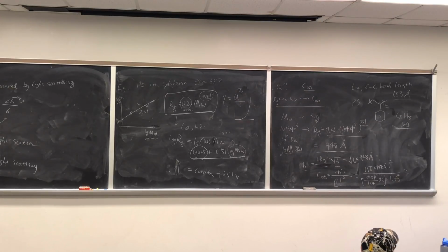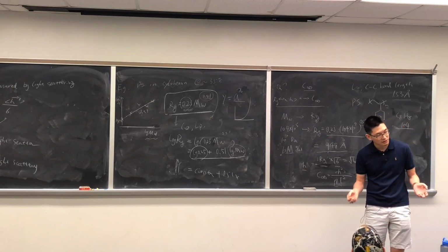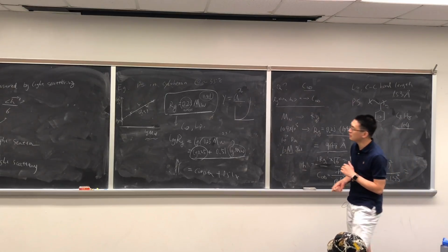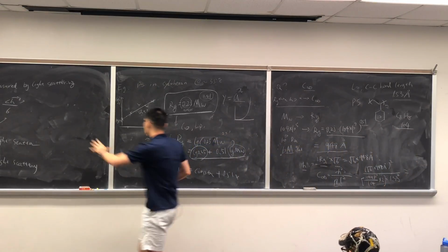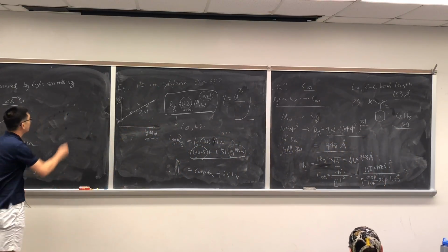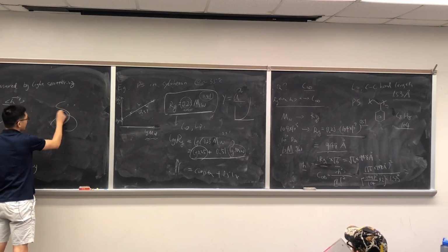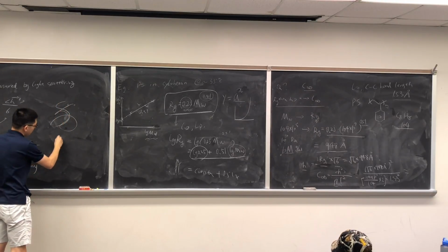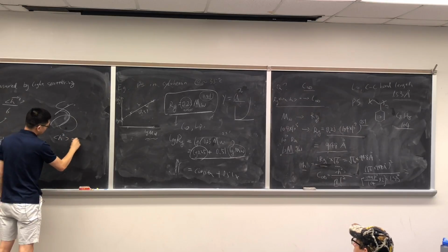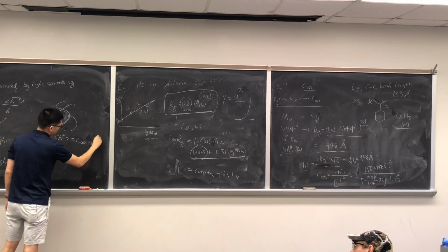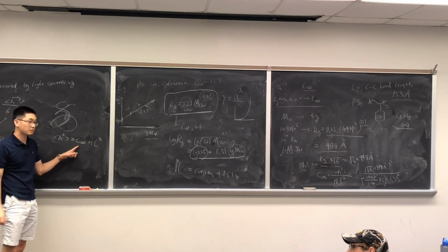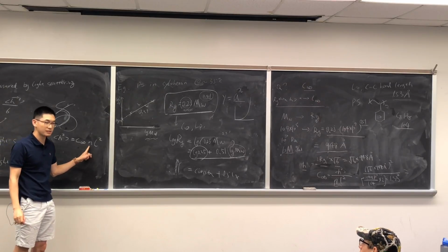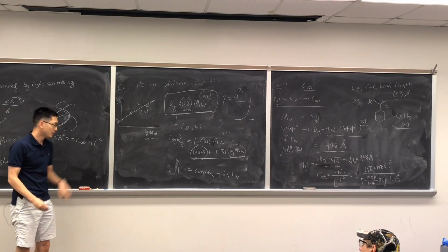I just still think that if n was the number of repeating... Wait, so n. Throughout the early class courses we talked about two models we can use to describe a chain. So let me use this empty space. If you have a chain, you can describe h square where we see C infinity n L square. So this will be the characteristic ratio, number of bonds, and individual bond length. So n is the number of bonds.